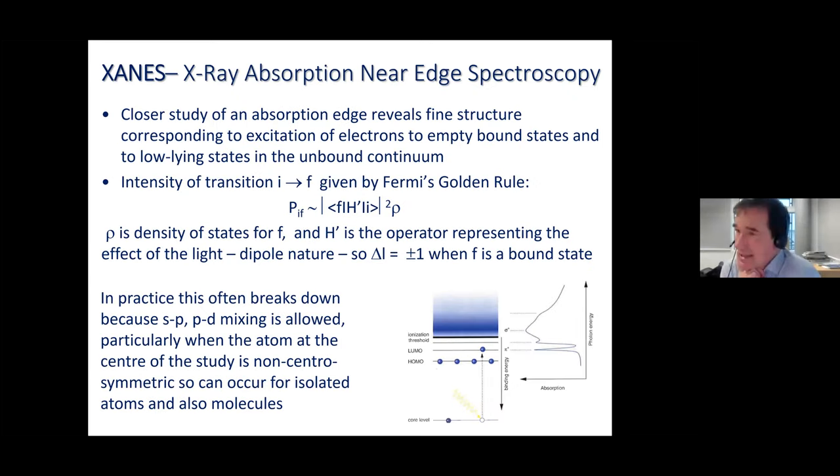So we'll start off with XANES and think about what is going on in the XANES spectrum. Well, in the XANES spectrum, and we just look at this cartoon in the bottom right, of course, the electronic transition that we're exciting is from some kind of ground state into states which are just below or at the point of photoionization. Once you go well beyond that, you go well beyond the edge. So you could imagine that what this process probes is transitions into the electronic energy levels, the least tightly bound energy levels, those orbitals that are most involved in chemical binding.